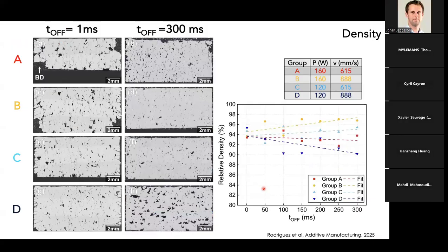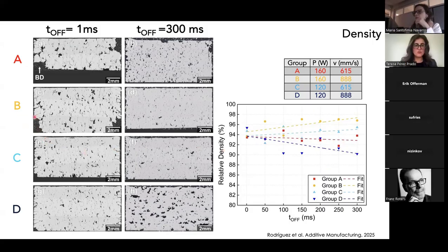So here I show you the density. We can see first in this graph the density versus the time delay, T-off, for the different groups. If you look at the orange and then light blue regions, it looks like, yes, if we introduce time delays, the density increases. For group A, red, at least it doesn't decrease much, and you can see that here in the micrographs. This is group B and C, the second and third rows, with the left column without time delays and the right column with time delay. You see that even qualitatively we can see an increase in the density. It doesn't work for group D because we are already in very low energy conditions. So if, on top of that, we let the layer cool down, basically we are in the lack of fusion region and we create more defects.